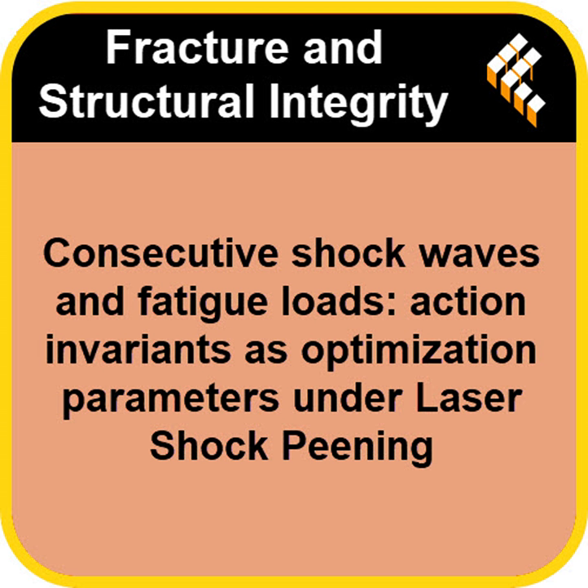All right, let's unpack that. Why exactly does residual stress fail us when we're dealing with LSP? Well, residual stress works okay for slower quasi-static loading, things below maybe 10 per second strain rate. But an LSP shock wave blows right past the material's normal elastic limit, the Hugoniot elastic limit, or HEL. Meaning it's not just squeezing it, it's fundamentally changing it instantly. Instantly. You get intense plastic deformation, the microstructure rearranges itself in nanoseconds. It's a mix of ductile flow and brittle cracking happening almost simultaneously. It's complex. Chaotic even. Definitely chaotic and non-local.